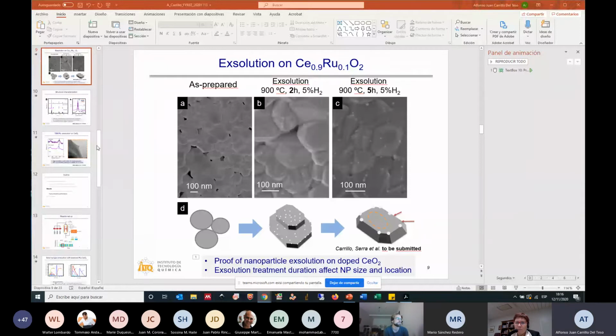Well, we checked the anchoring of the nanoparticles by TEM, as I showed later. For the materials with these lighter nanoparticles, we didn't look at them much more after we saw that it was better to just do 2 hours of exsolution. Time-wise it was better, and the dispersion of the particles looked also better than the other case.